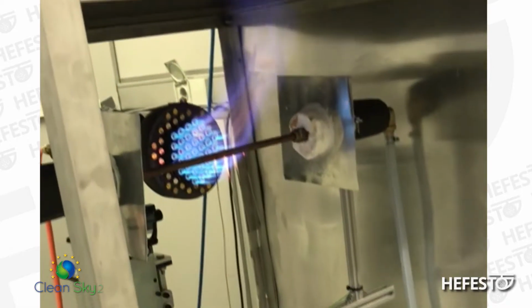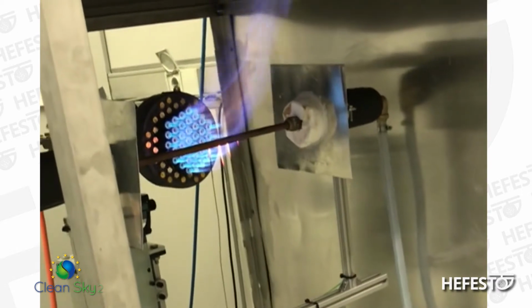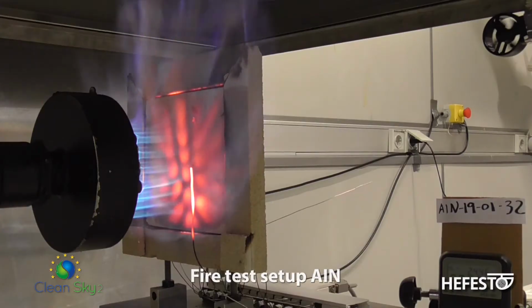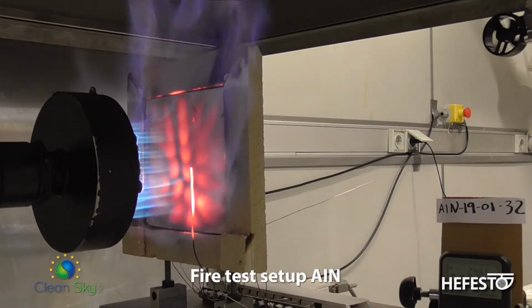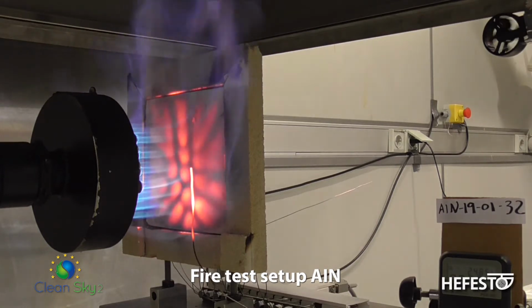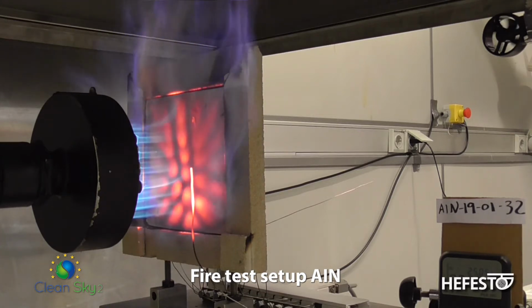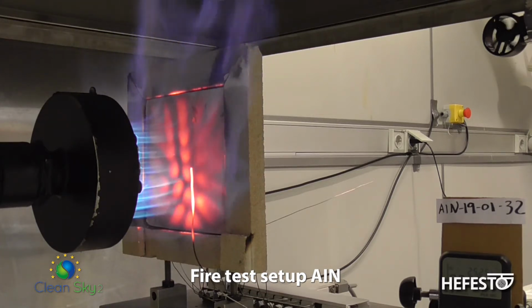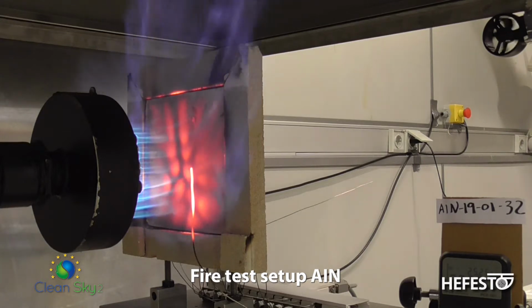The test setup mounted in AIN complies with the ISO 2685 of the aerospace industry, consisting of exposing the samples to a flame of 1100 degrees C during 15 minutes. The coupon is exposed to a flame with an impinging diameter of at least half of the area of the coupon, placing a temperature of 1100 degrees C and a heat flux of 116 kilowatts per square meter directly onto the surface of the coupon.